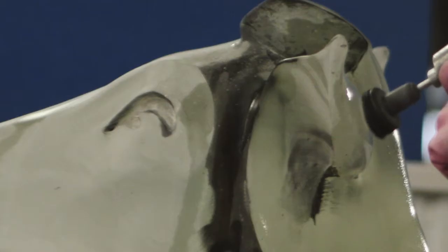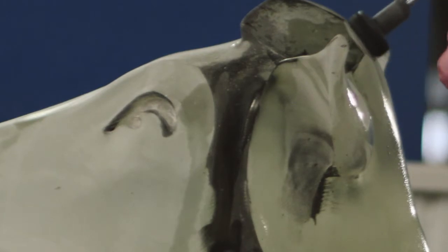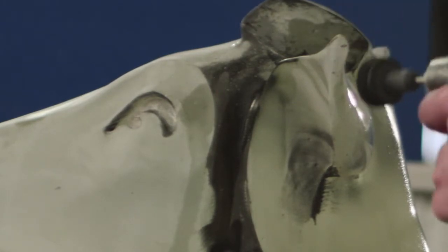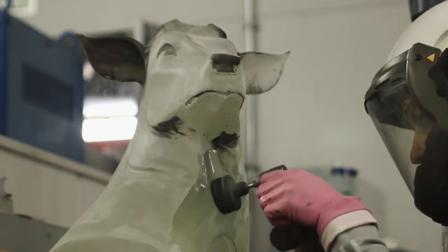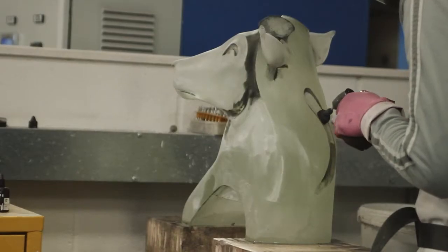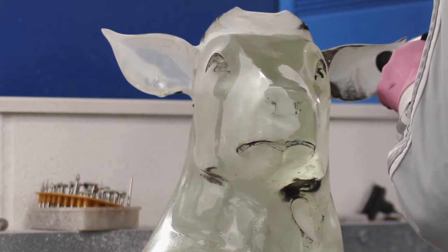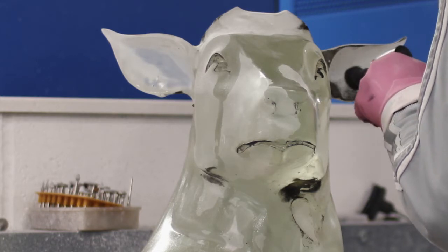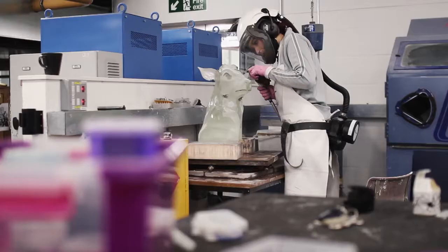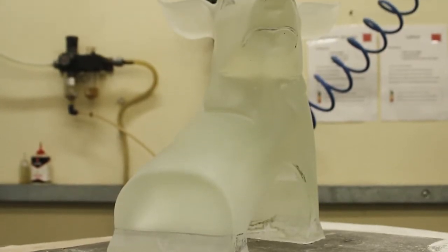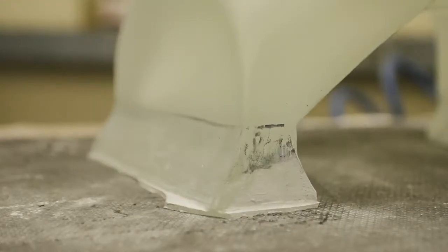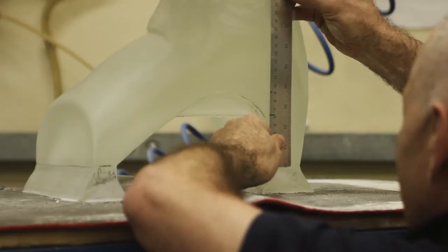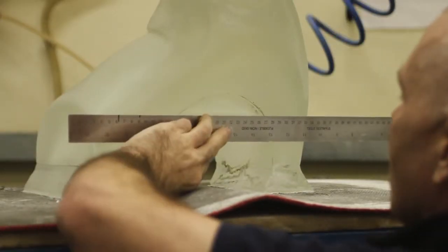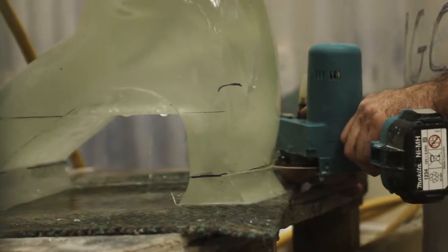So with 60 grit, which is quite rough, and that's to take most of the rough surface, and then I go 60, 80, 120, 220, 400. The final stage of the grinding is 400, which is quite smooth. The antlers go through the same process. We remove the reservoirs with a hand saw, and once Matt finishes to remove the reservoirs, we hand lap it just to get it nice and even.